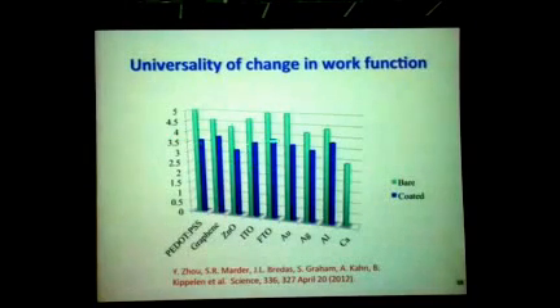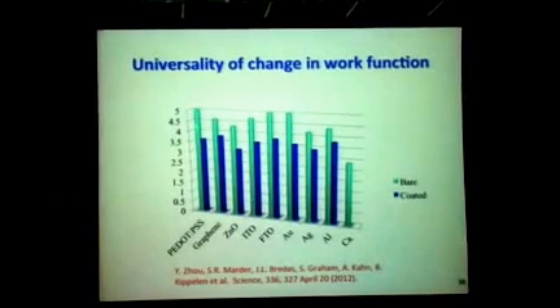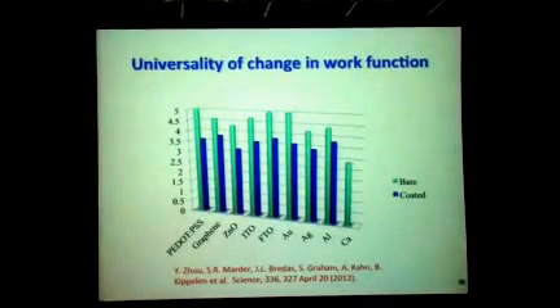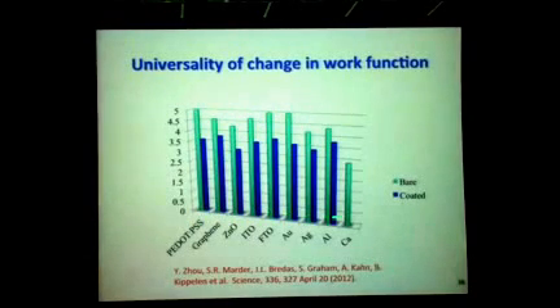So here's just a summary that shows the method is fairly universal because it's physisorption as opposed to chemisorption, so it doesn't really depend on the chemistry of the surface. You can see the green bars here are the initial work function values of various electrodes, and after PEIE modification, you can see the significant change. It drops with zinc oxide, for instance. You can go down to 3.1 eV, which is very close to what you have with calcium.